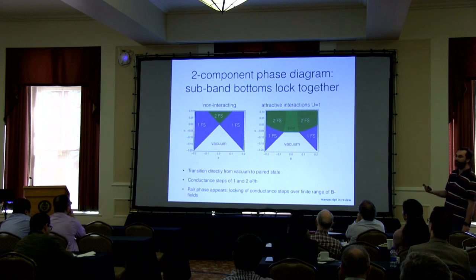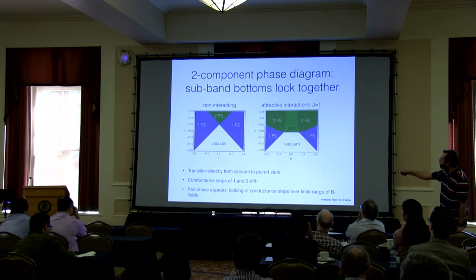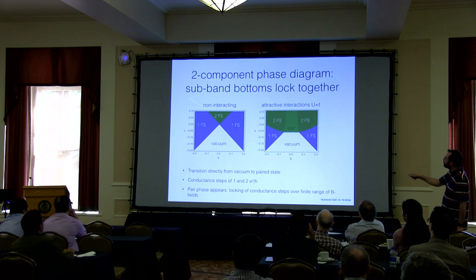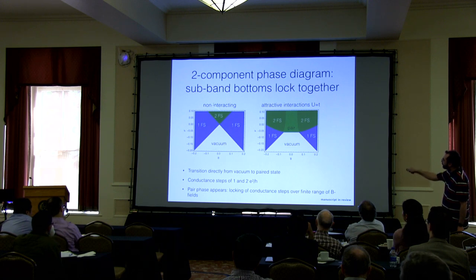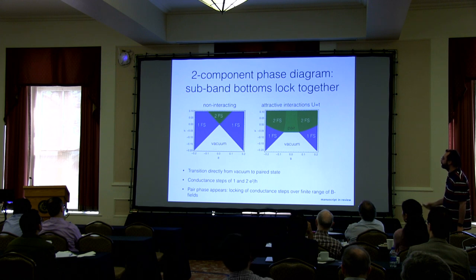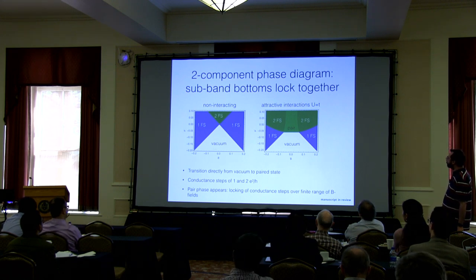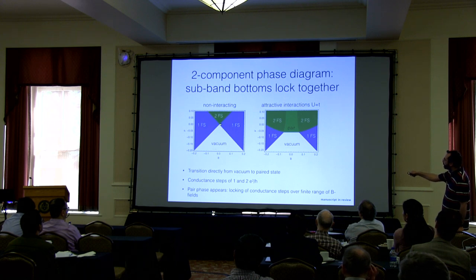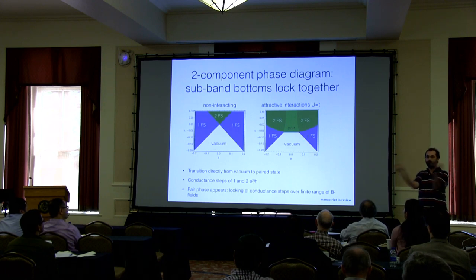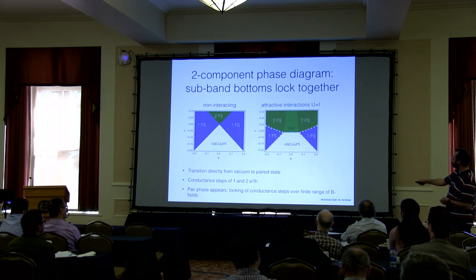So let's first start with this easy case, two components. On this axis is plotted the chemical potential and magnetic field. And first, let's do the non-interacting case. Well, we have one component which gets filled above this line, another component that gets filled above this line. And here we have both components being filled. So we have a phase with two Fermi surfaces, but they're non-interacting. Now, what happens when we turn on attractive interaction? Well, this phase becomes unstable. And what it becomes unstable to is a pair phase, where pairs of different types of fermions bind together. So we have a Luttinger liquid of pairs. So in this case, we can have conductance steps of one quantum of conductance, but we can also have conductance steps of two.